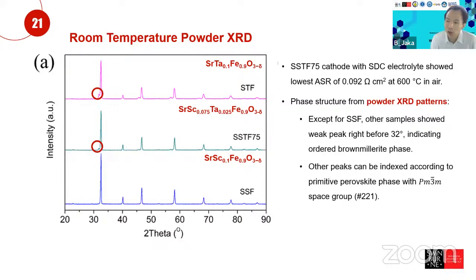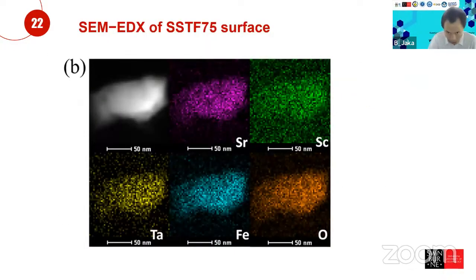Okay, what other conclusions can we take in here? Except for SSF, the other samples show a weak peak before 32 degrees, which comes from the Brownmillerite phase, and all the peaks in here can basically be indexed according to the primitive perovskite structure with a space group of Pm3m. This one is showing the SEM EDX, meaning that all the components are distributed homogeneously, present in very uniform distributions all over the SSTF 75 sample that we have in here.